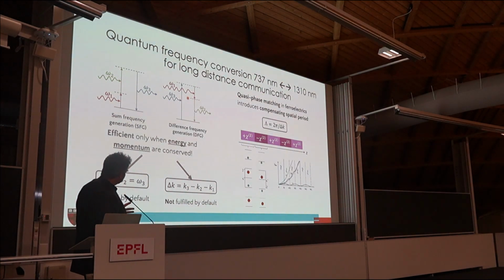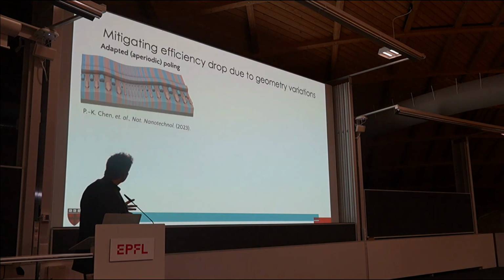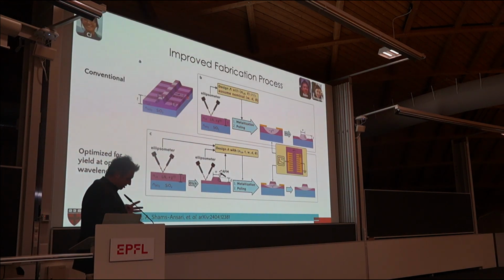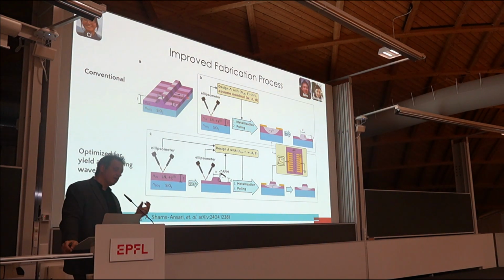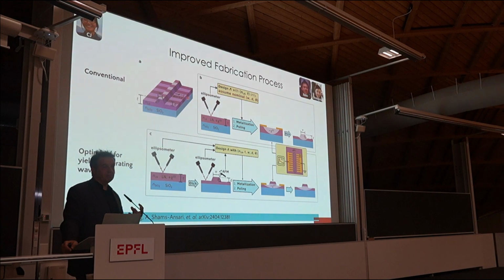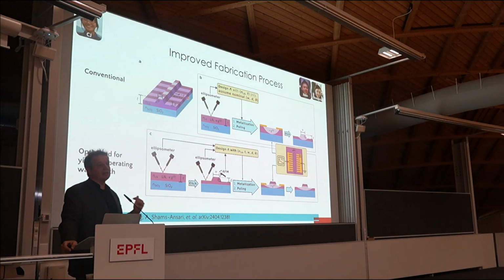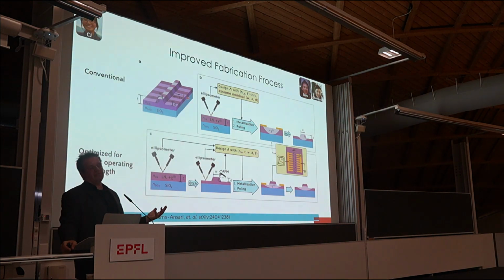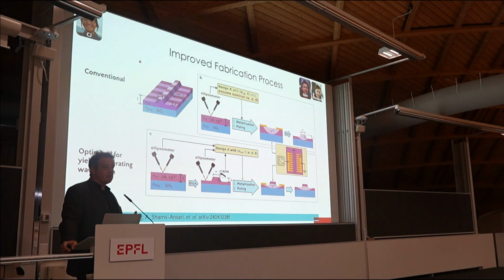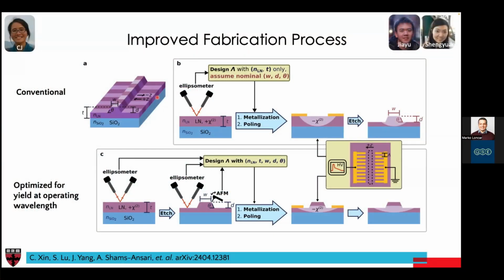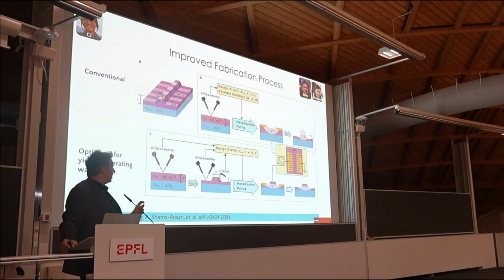And then thickness variations in this lithium niobate. Thickness variations in thin film lithium niobate are roughly plus or minus 20 nanometers in the starting material, because it's not well developed. That is enough to mess up your fabrication process and the performance of these devices tremendously. So typically people make thousands of devices and then cherry pick 5 that work. We were looking into ways to make this a scalable platform, and we have developed a process that combines a lot of metrology to get information about the thickness variation, and then we use this information to adjust the period of the poled structure so that they work perfectly, basically.